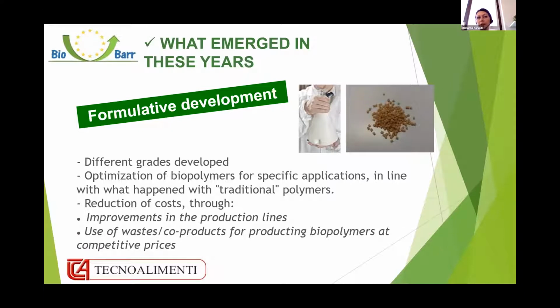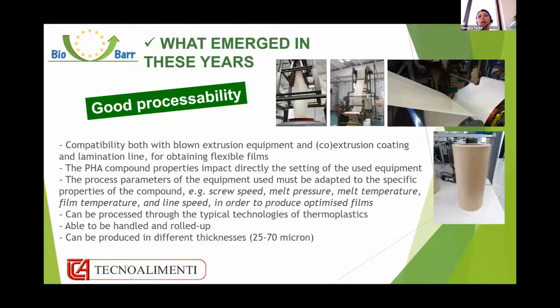In terms of formulative development, different grades have been developed. We were able to reduce the costs through the improvements in the production lines and the use of wastes and co-products for producing biopolymers at competitive prices. In terms of processability and runnability, we demonstrated the compatibility of PHA both with blown extrusion equipment and co-extrusion, coating and lamination lines for obtaining flexible films. We understood that the PHA compound properties impact directly the setting of the used equipment. The process parameters of the equipment used must be adapted to the specific properties of the compound.